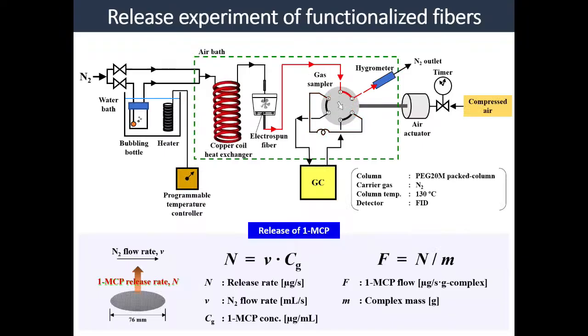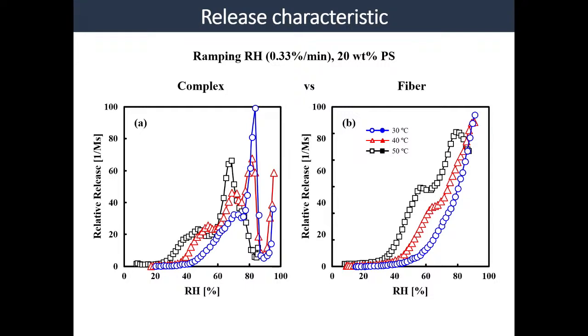I want to change that. So from those inclusion complexes, when we want to see the release under high humidity conditions, we can see the release of 1-MCP from the powder. But under low humidity conditions, we cannot see the 1-MCP release from the powder.